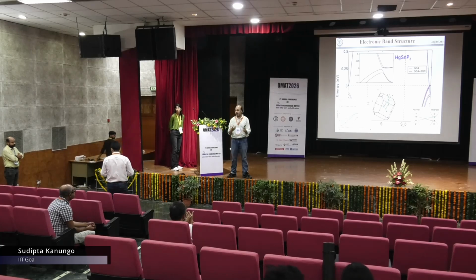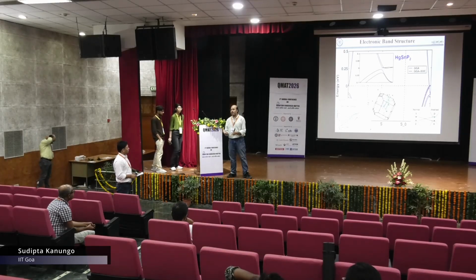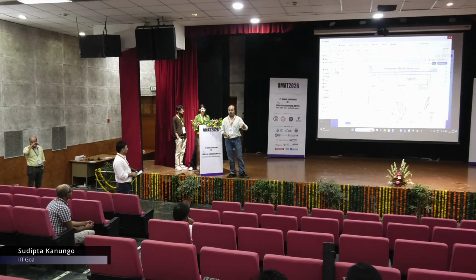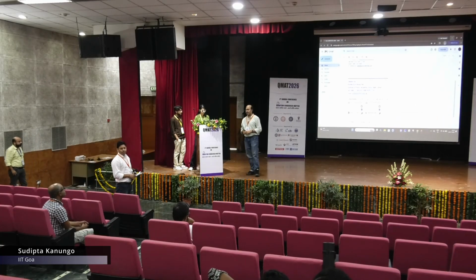You can ask why I am doing straining. Actually there is an experiment on the thin film, and the thin film is a strained system. So we try to mimic the thin film in our calculation by that strain. It is not actually a thin film calculation, just geometry straining, and we show that if we do that, we can enhance the anomalous Hall conductivity.